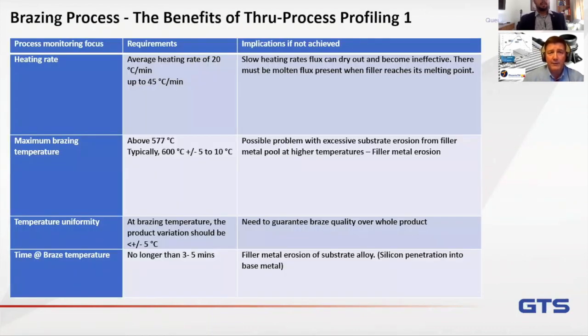Excellent. So we've talked about absolute temperature. Am I achieving the right brazing temperature to melt the alloy? But we've also got to be careful that we've got good control of the heating rate of the process as well. Particularly when we talk about the flux process, which is critical to the surface preparation of the aluminium. If you don't heat that at a uniform rate, if you heat it too slowly, the flux material will tend to dry out preferentially, and it will then be less effective in cleaning the surface of the aluminium.